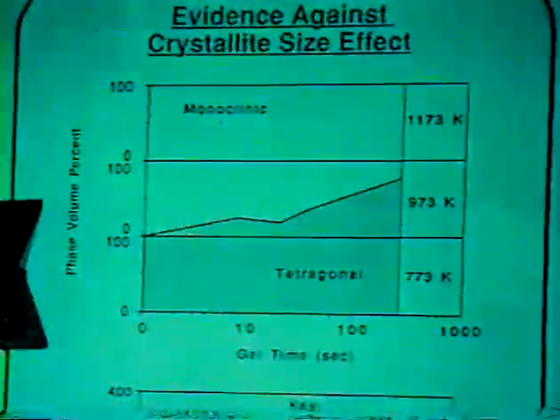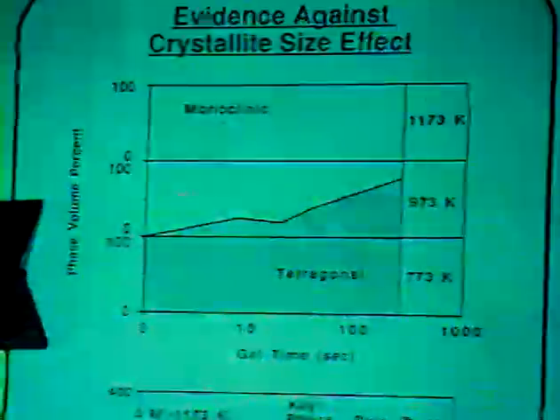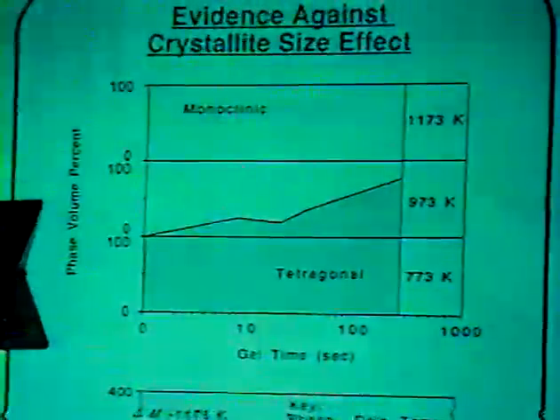At the same time, when we look at the top diagram, in which we actually monitor the fraction of tetragonal zirconia transformed into the monoclinic form, we observe the following. At 773 K, all the materials are stabilized in the tetragonal form, irrespective of the gel time at which the material is prepared. Also, by the time we reach 1173 K, all material has transformed into the monoclinic form. In the intermediate heat treatment of 973 K, we observe a very interesting trend. Namely, the fraction of conversion from tetragonal form to monoclinic form is a function of gel time.